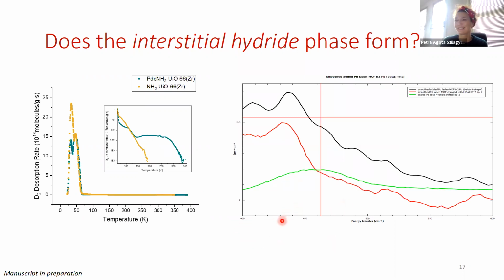Let me very briefly talk you through what you see here. In green, this is the palladium hydride spectrum in the relevant energy range. And in red, you have the spectrum of the palladium-laden amino UiO-66 under hydrogen. And the black spectrum is a convolution of 3 different components, and this is a simulation we did. On the one hand, we have this palladium hydride spectrum, which is exactly scaled to the amount of palladium that is present in the palladium-laden amino UiO-66. We added this to the palladium-laden amino UiO-66 framework in vacuum. And the third component is a kind of generic hydrogen in MOF spectrum, which we generated by measuring the spectrum of the empty amino UiO-66 in vacuum and under hydrogen.